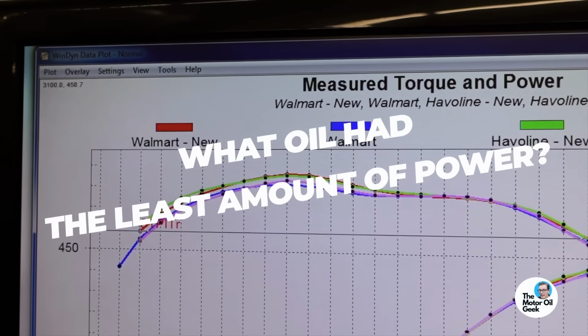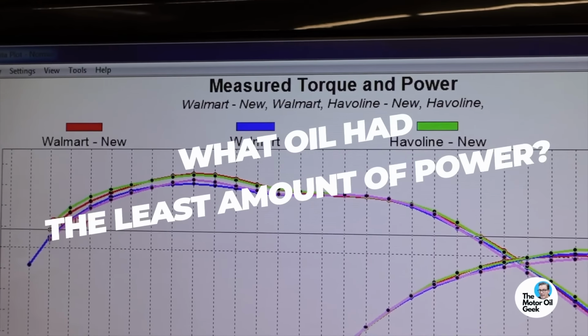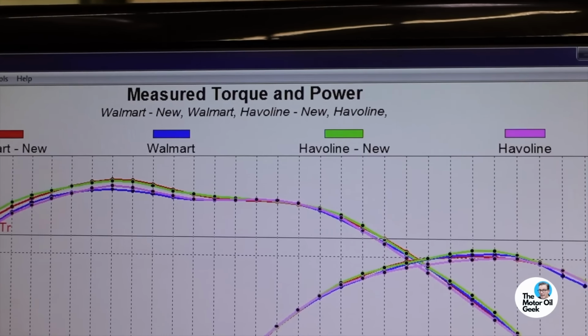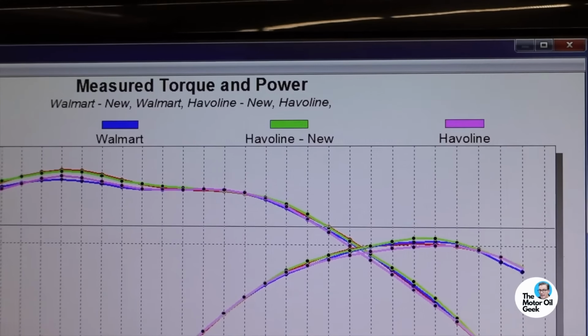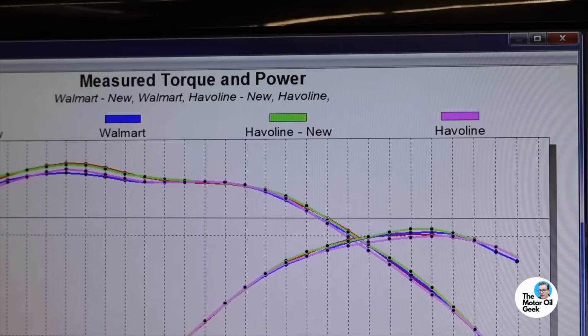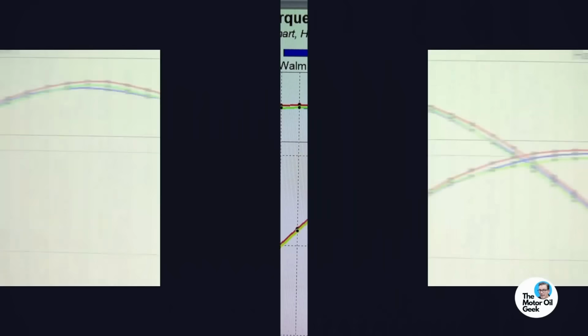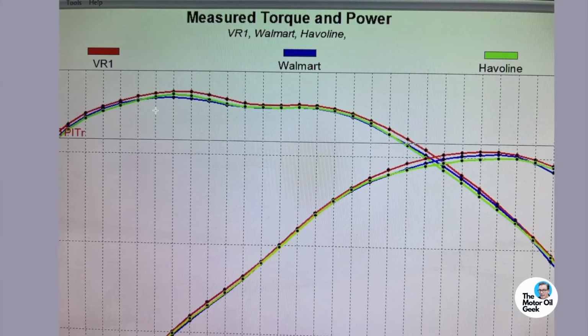What oil had the least amount of power? It was the conventional. These numbers are super, super close. It looks like they printed over each other, which is what happened. There's not a big variation between the three oils. But we do know that this engine dyno is incredibly consistent. So we can say that the Havoline was slightly lower in power than the SuperTech, and the VR1 was slightly more than the SuperTech. But it's pretty clear: the SuperTech beat the Havoline.